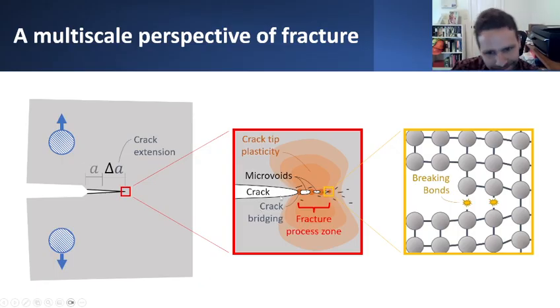But what's fascinating about this is that if you were to actually look at the material at this level of detail and at this scale, you'll notice that as the material starts to deform around this localized crack tip, if it's steel or any other kind of material that undergoes even just a little bit of plastic deformation, there's a lot of localized plastic deformation and plasticity occurring in the local vicinity of the crack tip. And depending on the behavior of the material, whether it's very brittle or very ductile, this zone of plastic deformation will be relatively small in the case of brittle fracture, or relatively large in the case of ductile fracture. But in either case, you'll definitely have some localized plastic deformation because the stresses in the vicinity of the crack tip tend to be very high compared to the stresses throughout the rest of the body. And we'll see exactly what that looks like in subsequent slides.